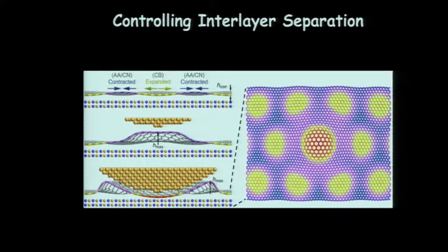And so the graphene wants to slightly expand to match the carbon with the boron in some region, and then it contracts here when the carbon is over the nitrogen sites. So there's already this slight lattice distortion. And now there's an interaction between the tip and the graphene. And we can be in different modes. We can be in the mode where we're far away from the substrate. There's a van der Waals interaction between the tip and the graphene, which pulls the graphene up a little bit.